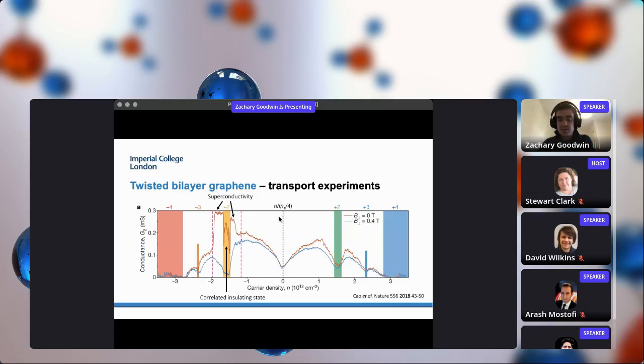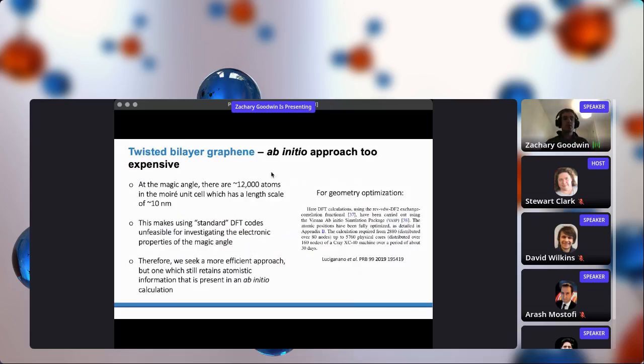Yeah, and so to understand these phases, one of the methods that one might use to investigate the electronic properties is an ab initio approach. But in fact, there are quite some challenges with doing this because at the magic angle of twisted bilayer graphene, there are about 12,000 atoms in the moiré unit cell, which has a length scale of about 10 nanometers. So using a standard DFT code is quite unfeasible to routinely investigate the electronic properties of this material. And as an example, I can show a published abstract, which basically shows that doing a geometry optimization for a magic angle system requires about 6,000 cores for about 30 days, which is really quite a heroic effort to investigate this material.